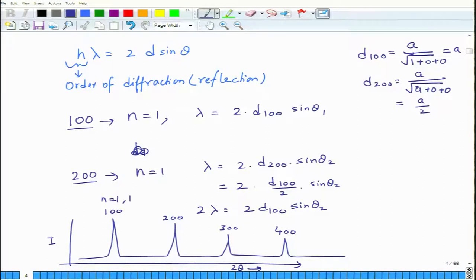So, this n, which is called as order of reflection, is meaningful in this manner. So, this is nothing but n is equal to 1 for 100, this is n is equal to 2 for 100, this is n is equal to 3 for 100 reflection, okay, and this is n is equal to 4 for 100 reflection, okay. Basically the order of reflection, the same plane can give you diffraction peaks at different angles. So, there may be no atom sitting at 100, 200, 300, 400. It is just that the wavelength is now diffracting in such a manner, so that first it was lambda, then it became 2 lambda, then it became 3 lambda, then it became 4 lambda.